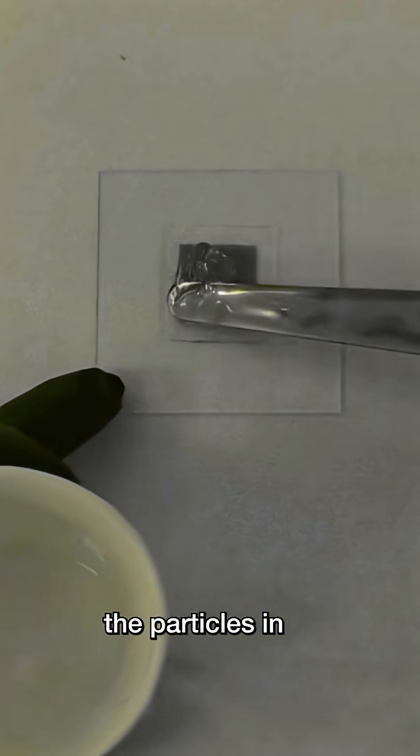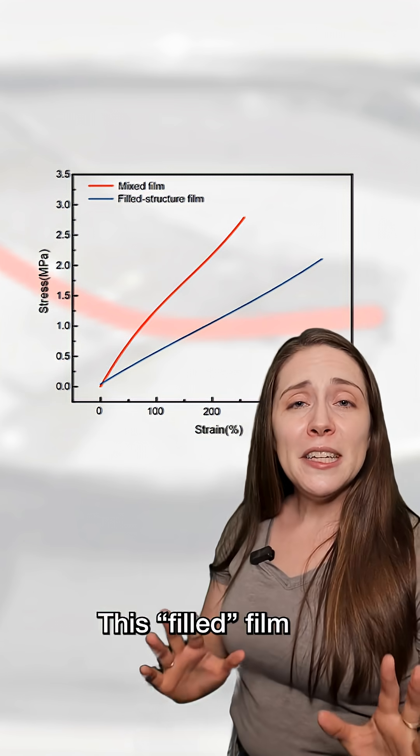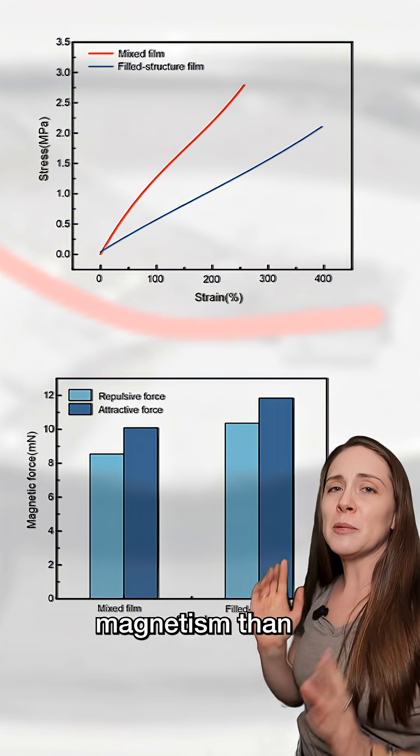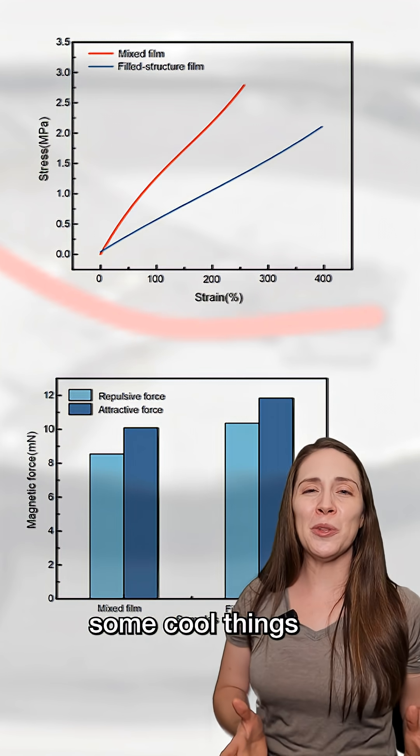instead of mixing the particles in evenly as usual. This filled film is twice as flexible and has almost 20% stronger magnetism than the mixed film, so it can do some cool things like this.